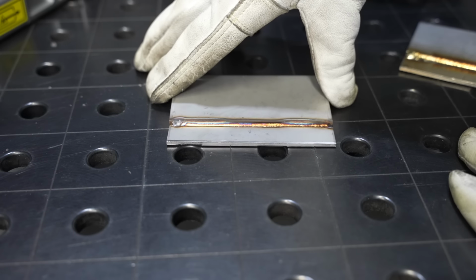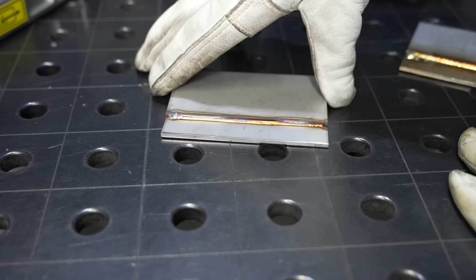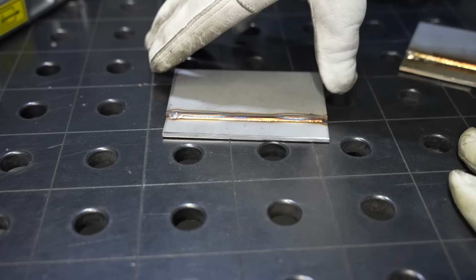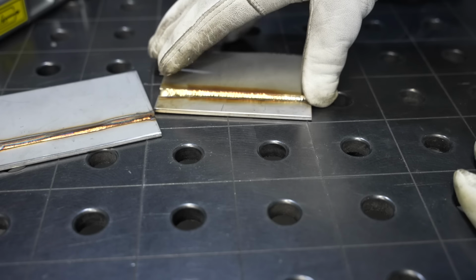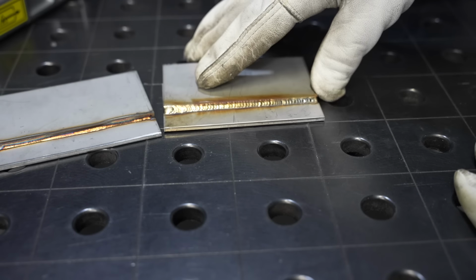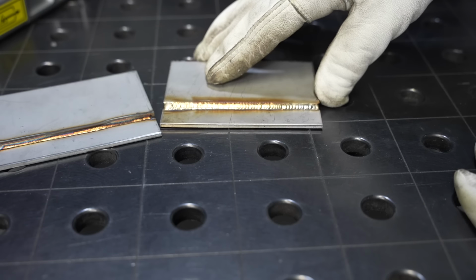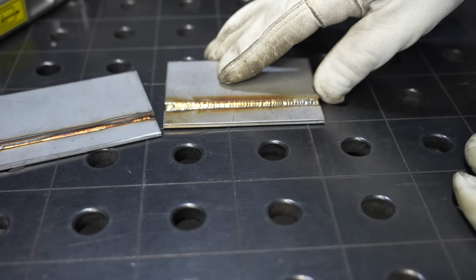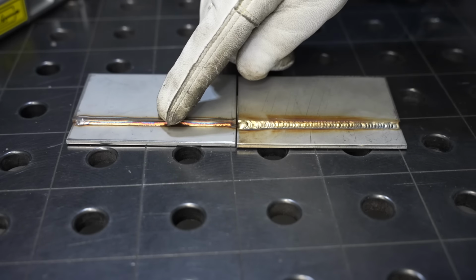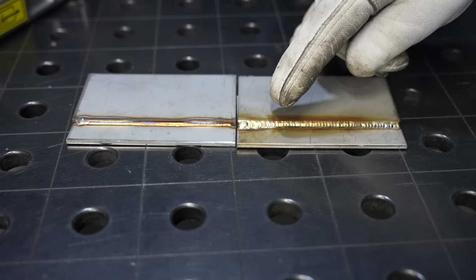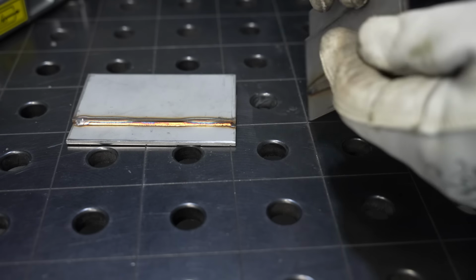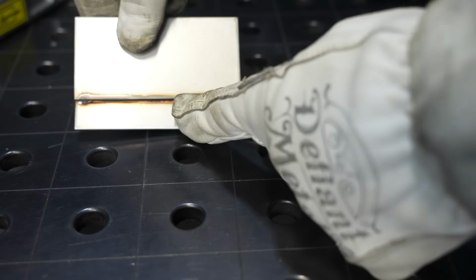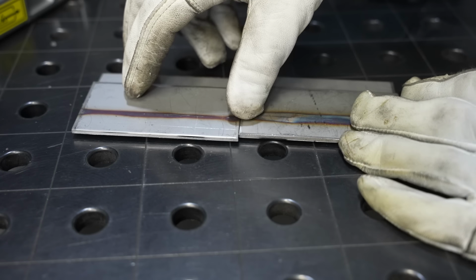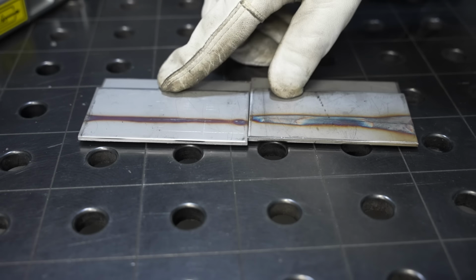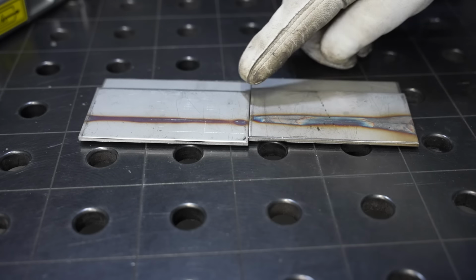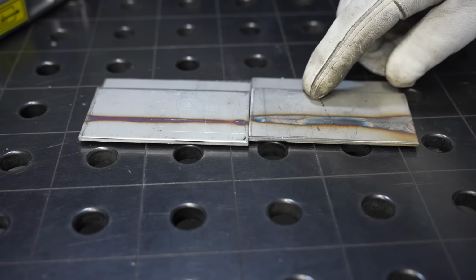Well, that was definitely a lot faster and easier than the TIG weld. I mean, that took just a few minutes to learn how to do, where running a TIG weld like this, and I'm certainly not the very best at it out there, but this took me a long time to be able to do. Now, there's a little bit darker color here because I didn't have a big 15 cup like I did on the TIG weld, but if you flip it over, it's pretty clear based on the heat tint here that there's a lot less heat input with the laser than there is with the TIG weld.